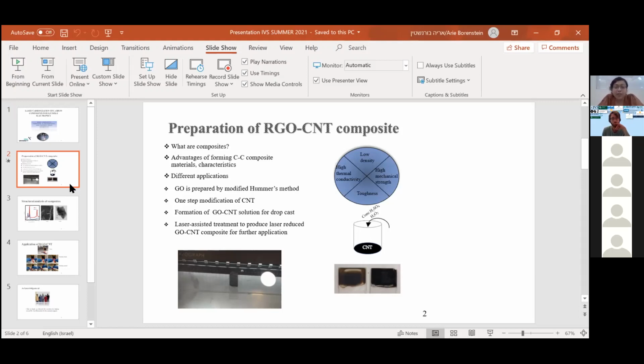GO in our lab is produced by the modified Hummers method, and the CNT is a rolled up sheet of sp2 hybridized carbon, and it doesn't have any effect on the laser carbonization. So we need to modify the CNT, a one-step modification of the CNTs to build the carbonyl groups or higher oxygenated groups on the surface of the CNTs. Next come the laser carbonizations of the GO-CNT composite to form the RGO-CNTs.